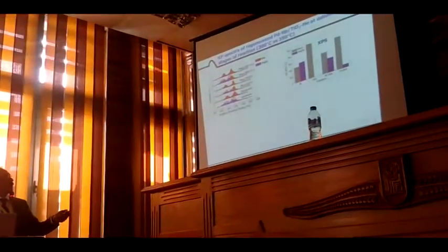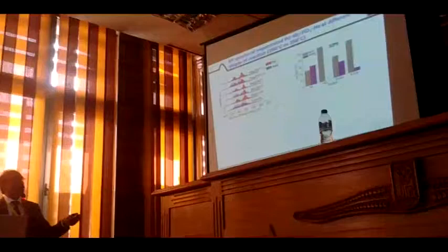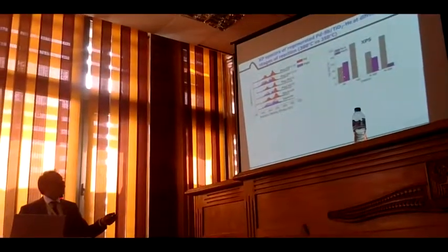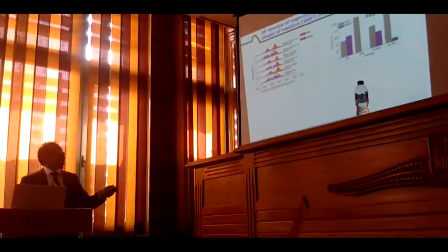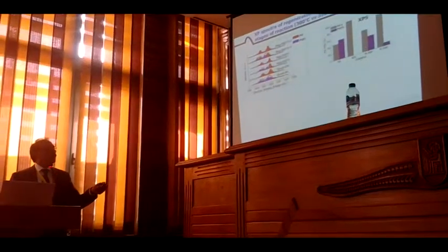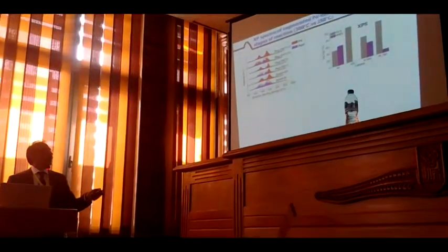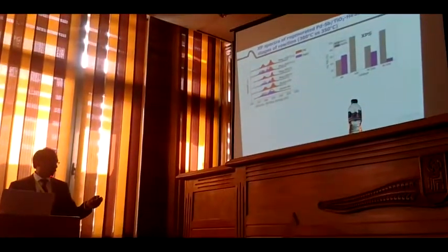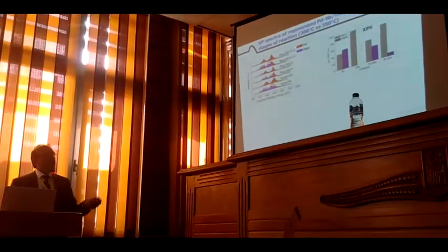So in the fresh catalyst you have roughly 1 to 1, both palladium and palladium oxide, and the spent catalyst only palladium, and the regenerated at 300 you have both, and in the regenerated one at 350 you don't have it. This is the story of palladium. What happens with the antimony?